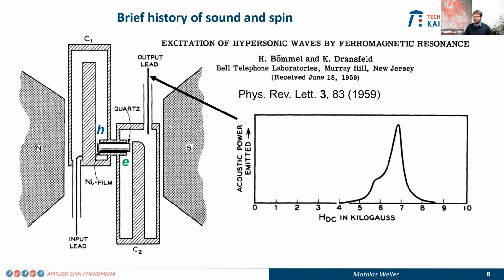First seminal experiments that go in that direction were done very shortly afterwards, the Bömmel and Dransfeld experiment, where they took a quartz rod that on one side had a nickel film, and the quartz rod was used to connect two microwave cavities with each other.